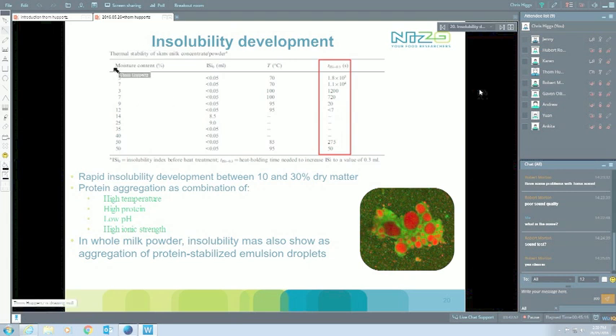If we do something like that on a dry powder, 3% moisture or something like that, nothing will happen. We can heat for extremely long times before we see anything happen. In the same case, if we do it on concentrates, 50% moisture, 50% dry matter, again, we can heat our systems quite long. We get quite extreme heating conditions, a couple of minutes at 85 degrees, a minute at 95 degrees, and even there very little insolubility is happening.